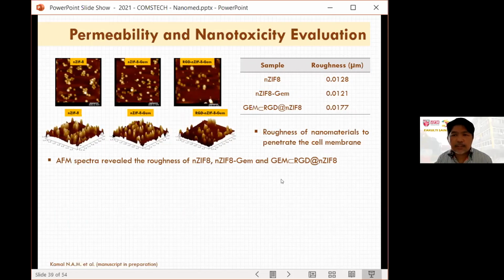Currently we are also looking at AFM, as not many people are working on AFM for MOFs. Since we have this equipment, we thought, why don't we look at this, and we can show that the permeability and nanotoxicity can be very much related to the roughness of the nanomaterial. For this one, the roughness is actually the highest, and it is able to penetrate the cell membrane.